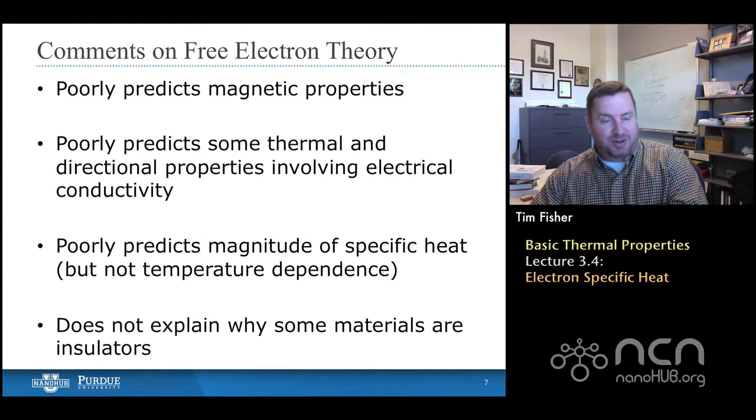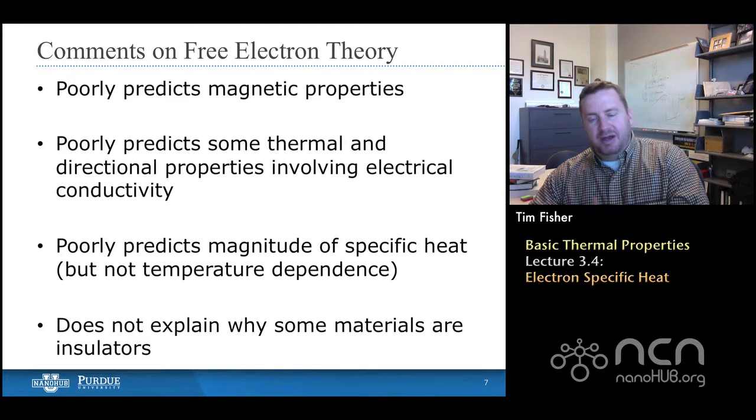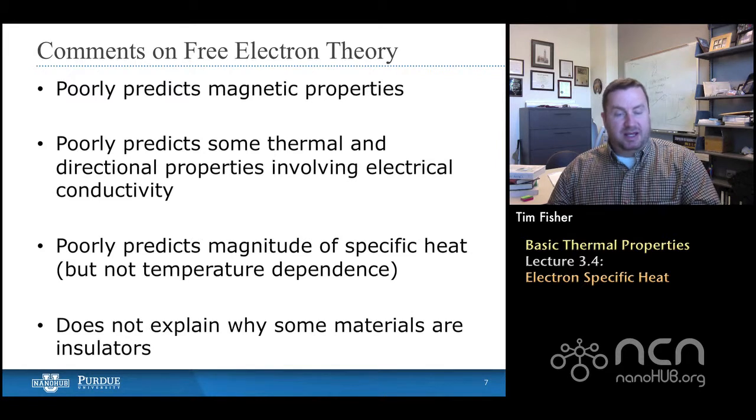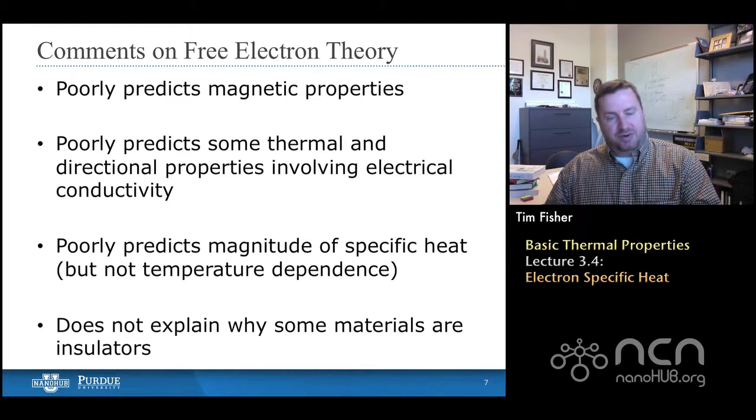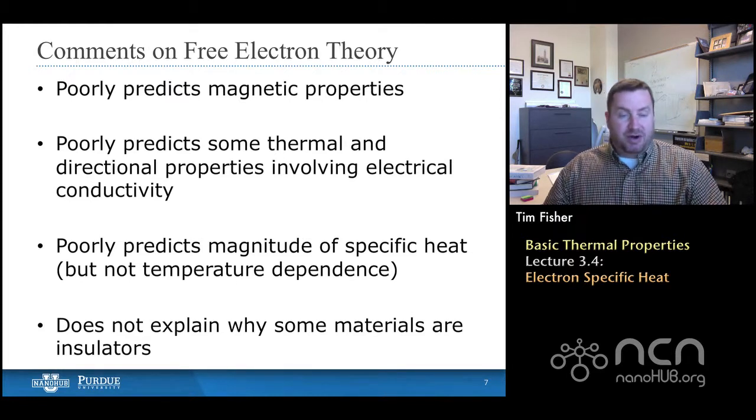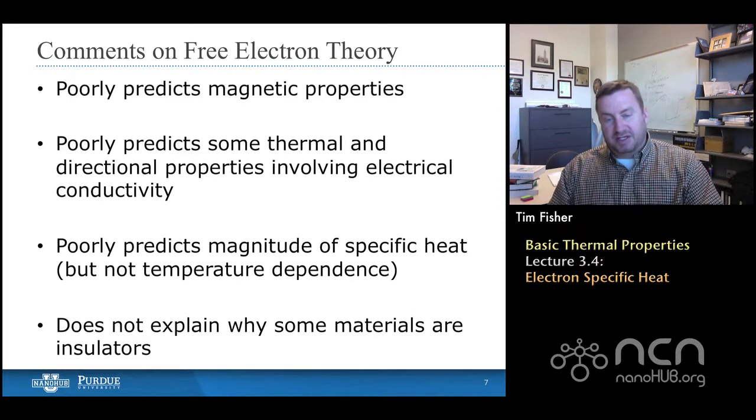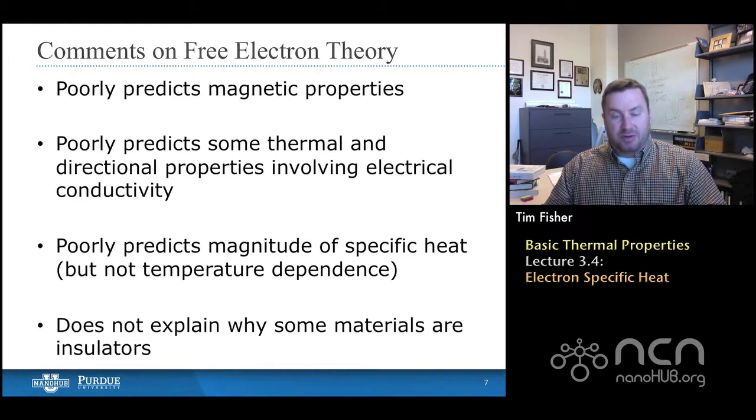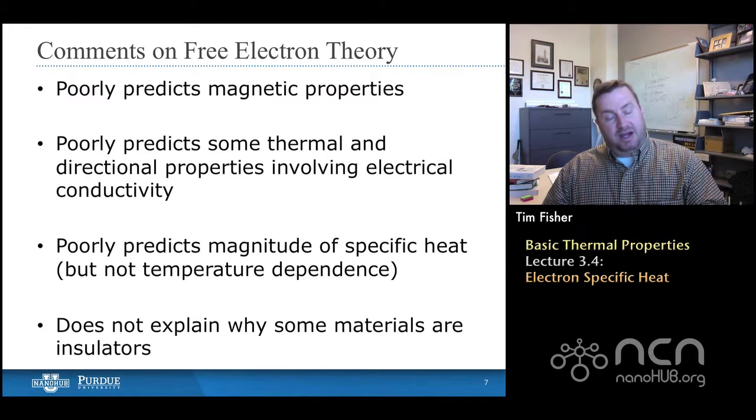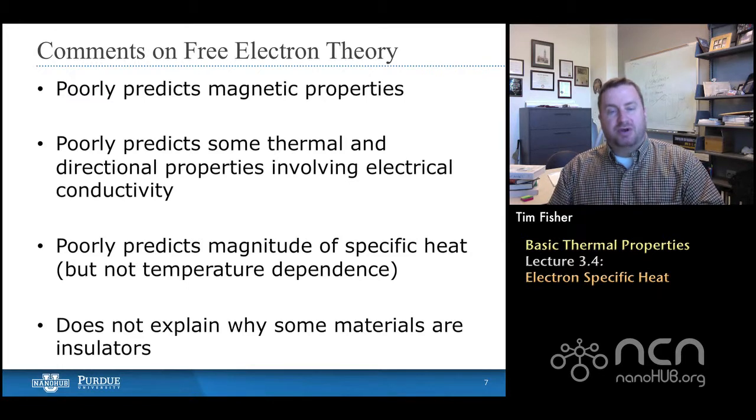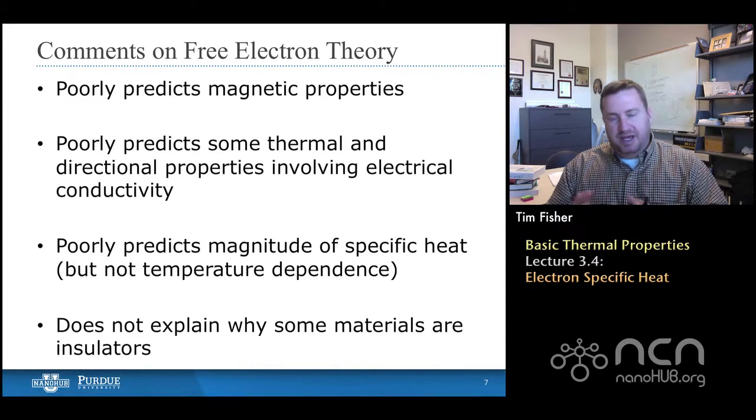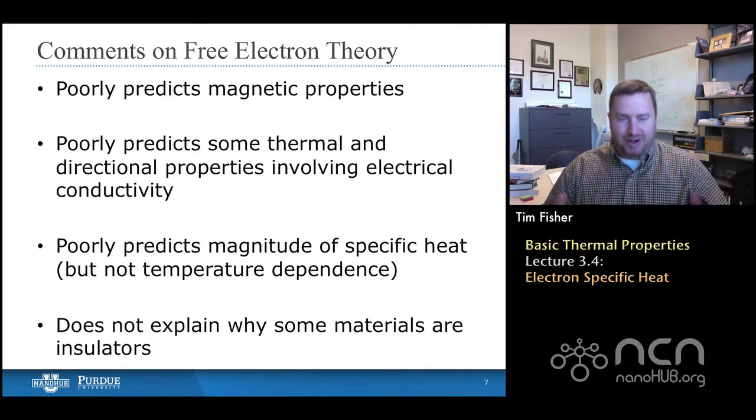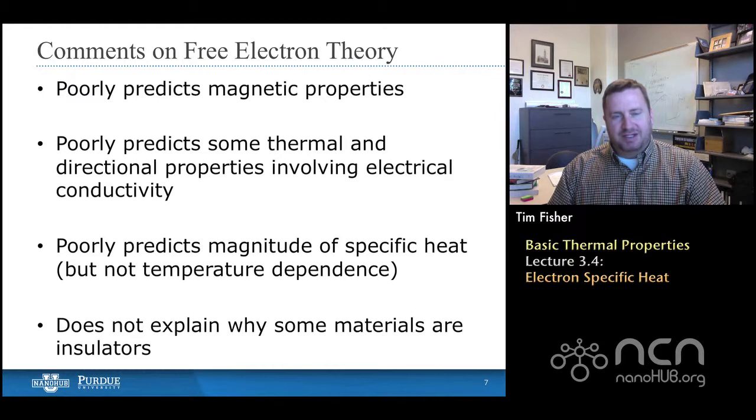And that's a major concern for electrical engineers. For what we do in thermal engineering, most of the time we'll say, if it's not a metal, if it's not a highly electrically conductive material, then the electronic parts of the transport properties are essentially negligible. And we'll just focus, and in those cases we focus on the phonon parts. In fact, there are some materials that are metals, formally metals, meaning that they have a non-zero density of states at the Fermi energy, and their electronic contributions to heat flow are much less than those of phonons. Carbon nanotubes are a good example of that. Even though they're metallic, some of them are, the ones that are metallic, even so, there's not a high enough electron density to make the magnitude of heat flow from electrons comparable to that by phonons. So, we'll cover a few of these things. We still have to add some other concepts like scattering to really bring all of these things together, and we'll get there soon enough. That'll be at least part of the topic for the next lecture. Thanks.